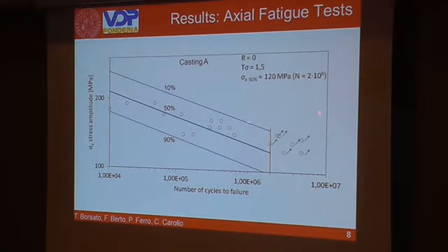Axial fatigue tests were conducted at room temperature with a load ratio equal to 0 on specimens that were taken from the same zone as the tensile test specimens. All the results have been statistically elaborated using a log normal distribution, and the Wöhler diagram is plotted. We can observe that the stress amplitude at 2 million cycles for casting A is equal to 120 megapascal, with a scatter index equal to 1.5.